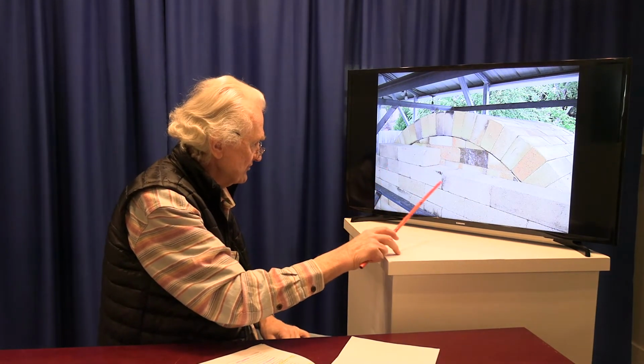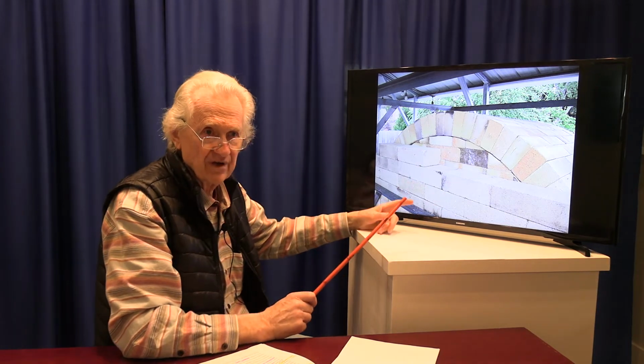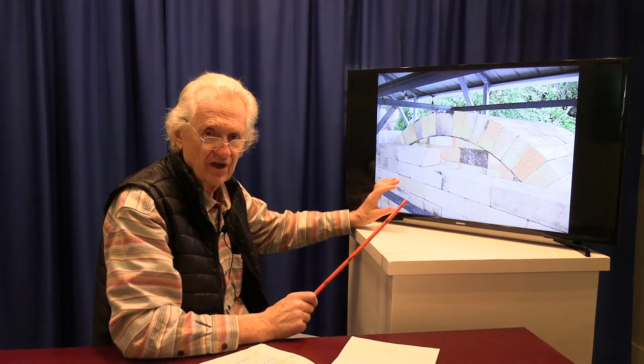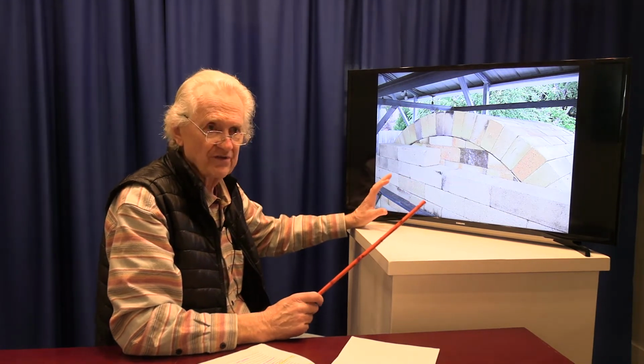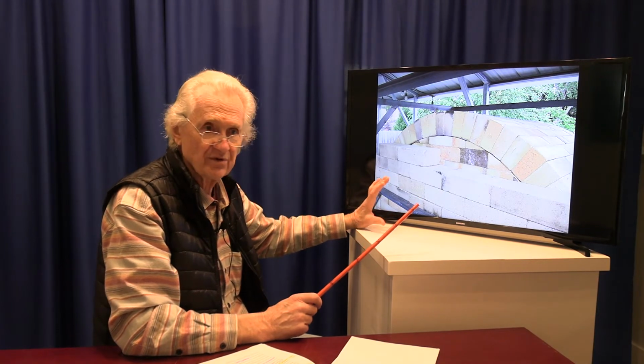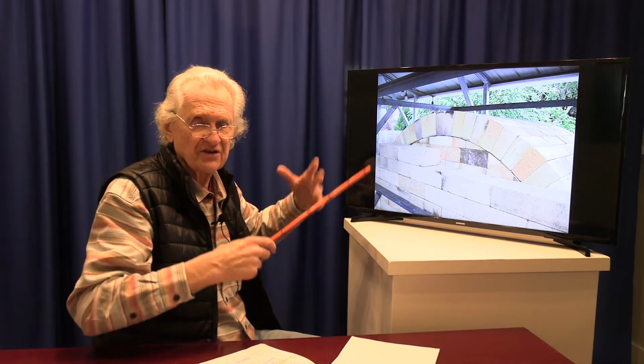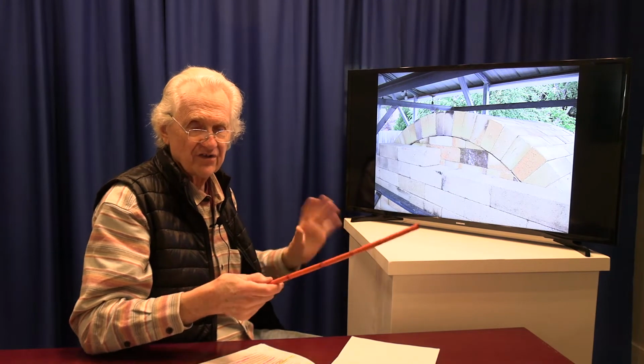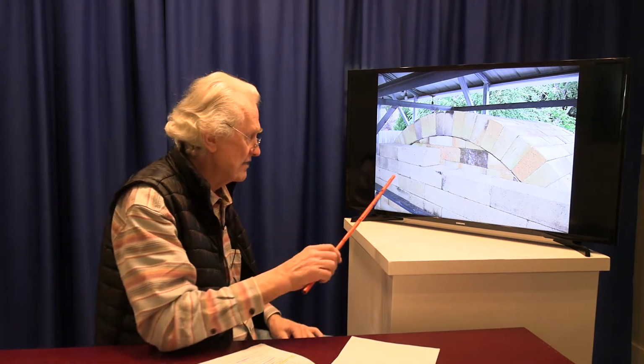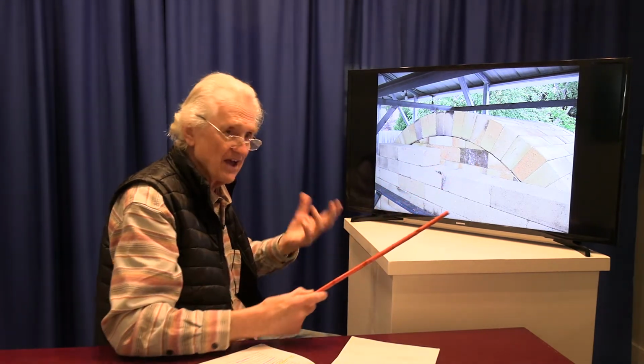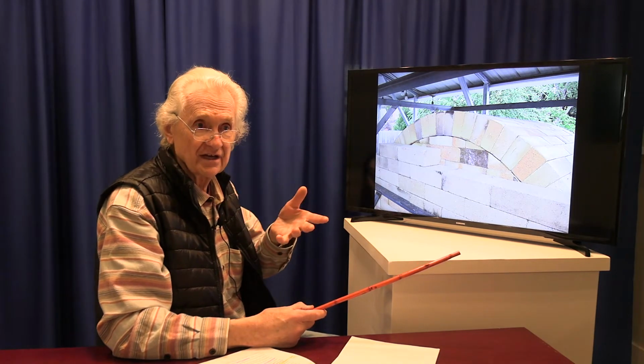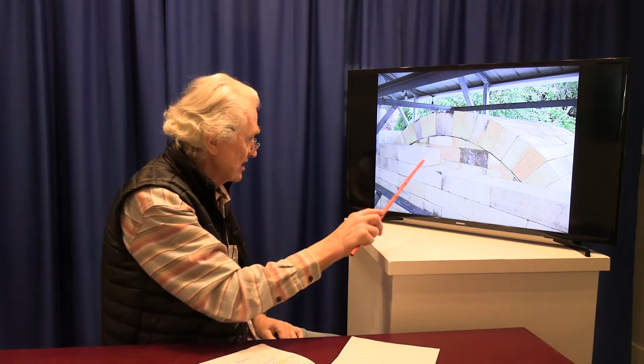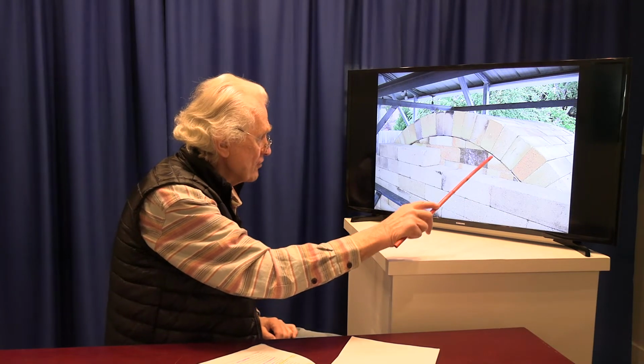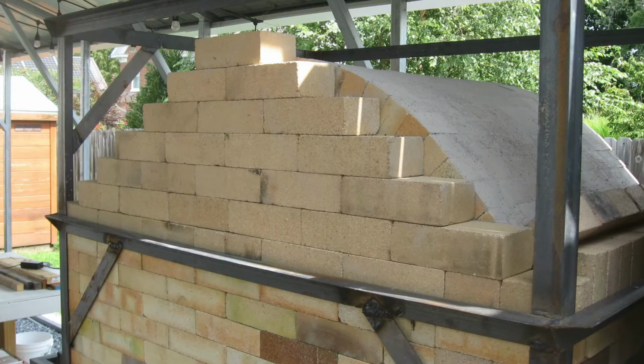So this is showing where we started. Now these are some other bricks that we had. These were 3-inch thick bricks that we just happened to have, and this was the perfect place to use them. These are high heat bricks, but they're 3 inches thick because they don't have to interlock with any of the other bricks. So the fact that they're a slightly different size didn't matter. So it was a good place to use them. And it's actually nice because then the joints don't line up, so we actually get a better seal. So we started to just stack them up over the face of the arch.